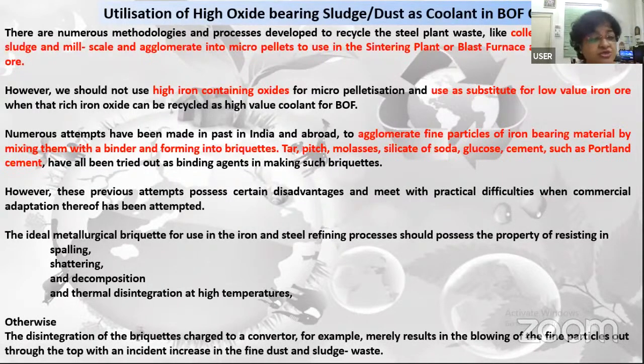We should not use high iron containing oxide for micropelletization and use it as a substitute for low value iron ore, when that rich iron oxide can be recycled as high value coolant for BOF, basic oxygen furnace. So numerous attempts have been made in the past, in India and abroad, to agglomerate those fine particles of iron bearing material by mixing them with a binder and forming them into what is called a briquette.